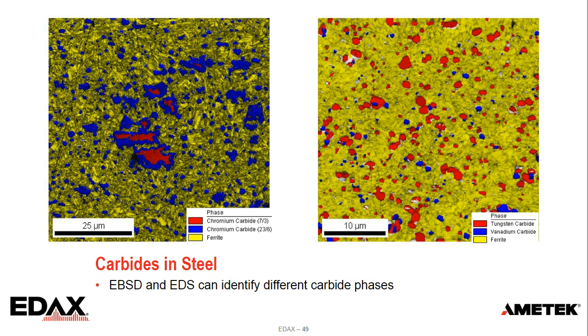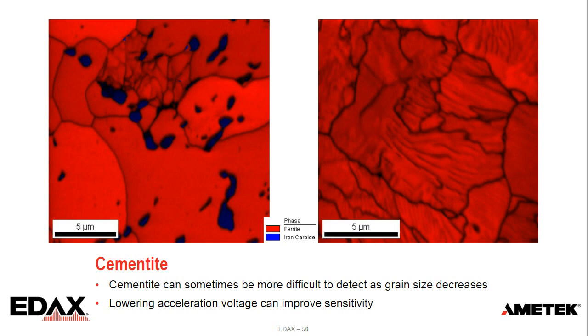But sometimes it's not always as easy. This is just an example from cementite. The image on the left, the larger globular cementite, those come out nicely. On the right here, this shows more of a pearlitic microstructure, where the bands of iron carbide are much finer, much smaller. So it can be more difficult to detect, especially with larger step sizes. And there's been work that shows that if you go to lower voltages, you can start to resolve that better. So you can get it, but sometimes it gets to be tricky, sometimes from a physics point of view, sometimes from a sampling point of view.